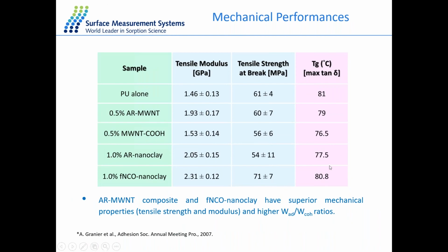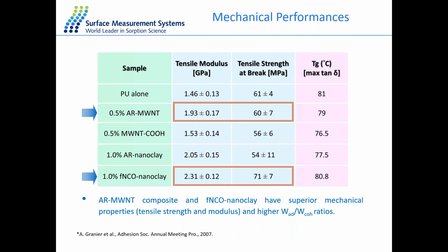We've also coupled this with another technique to understand the mechanical performance, and it's showing that with the higher work of cohesion, we have higher tensile strength. So it's very useful to correlate the data from the surface energy to work of adhesion and cohesion to other mechanical properties.